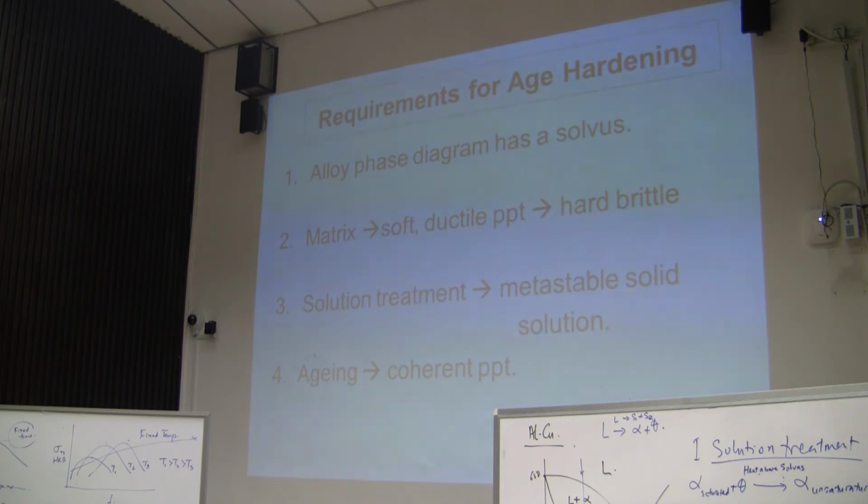So at first, you must go through aging. This aging must be done properly. Natural aging is okay. But when you do artificial aging, it is very easy to lose control and it becomes overaged. What is the cause of overaging? In a nutshell, your precipitate becomes incoherent.